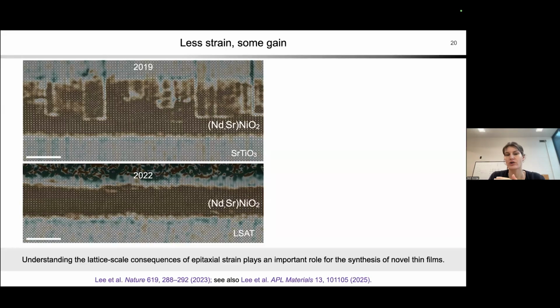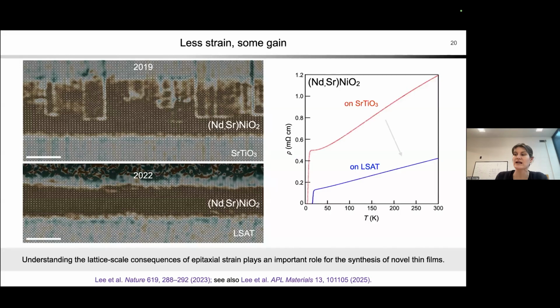And that's because these are grown on two different materials. It turns out that this bottom material, LSAT, has a better lattice match with the nickelate film, and so you're able to stabilize a higher quality structure. And it doesn't just look nicer in the electron micrographs, it also improves the properties of the materials, which is ultimately what we're really interested in, right? Having a nice material that does something interesting or useful. You can see in this case that the superconducting transition, that vertical line from the red to the blue trace, has gone up by several Kelvin. That's a really big improvement for the superconducting properties in these materials, which is directly related to understanding the lattice properties and the lattice structure as well.